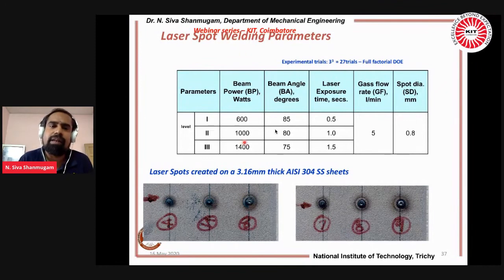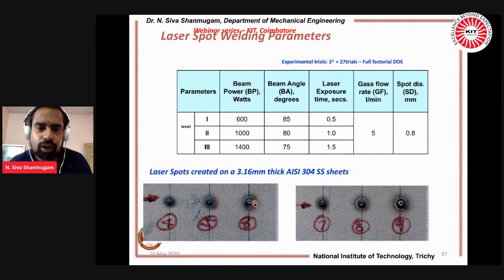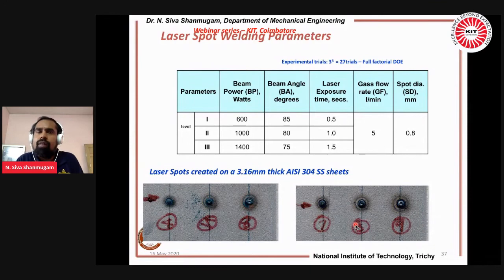So what are the input parameters? Now I can do the optimization to find out for which parameter set I am getting a very high depth of penetration, by doing the combinations. You see, with the different spot diameters, you can see the pinhole at the top surface. This is because of the keyhole. After removal of the heat source, the molten pool will close the entire keyhole, but it will leave the impression at the top surface. That is why it is called the keyhole technique.